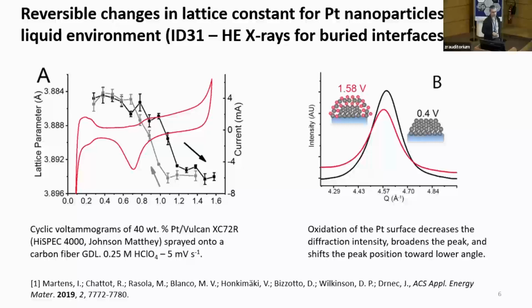Now I'm just shifting to the very same subject. Essentially, these are the associated changes in lattice constant. So in a fuel cell, we had a lot of talks this morning about this. Essentially, when you enter the surface oxide formation region, the lattice constant is also changing. So, for example, starting from this potential that we call the potential of zero total charge, essentially the potential at which the surface bears a zero surface charge density, and increasing the electrode potential, you make the metal surface more and more positive, and you start to attract first the anions, and then secondly, you start to adsorb OH species on the surface. And so what you see is that essentially the particle is like breathing. So the lattice constant is expanding.